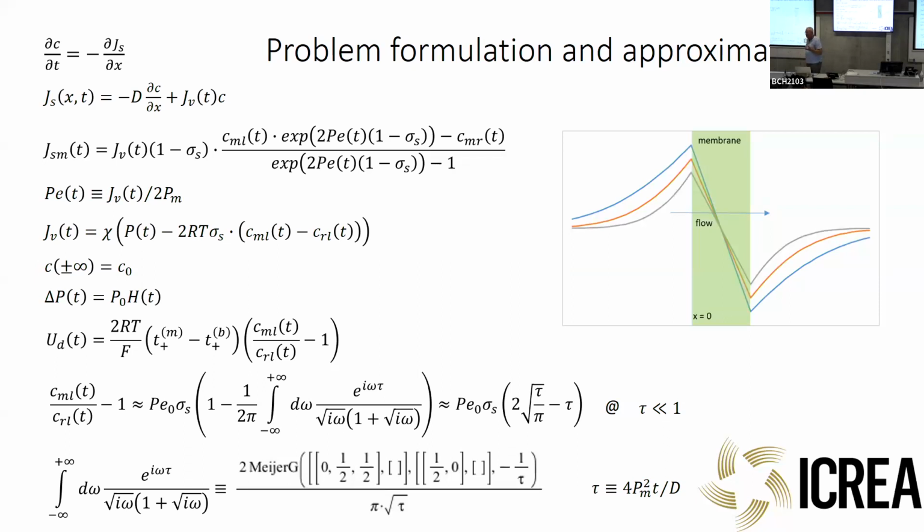And as we have seen, these voltages, for example, here we studied nanopores of 25, 35 nanometers in electrolyte solutions of 1 and 2 millimoles. So in this case, this additional voltage is several times larger than the initial streaming potential. So it's a major contribution.